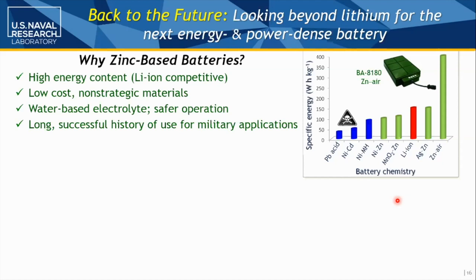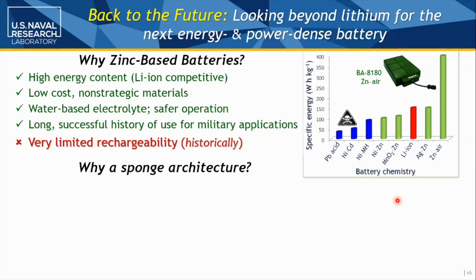So now we've got low cost, non-strategic materials. We're in an aqueous electrolyte. You've got a sweeter spot for manufacturability. You've got safer operation. And the military loves zinc. In fact, they often use one-shot discharge zinc airs to charge lithium batteries. But zinc systems are historically not very rechargeable. So when you bring our architected perspective and up the scale a bit, now we're not tens of nanometers, we might be tens of microns, back in the more standard battery size.